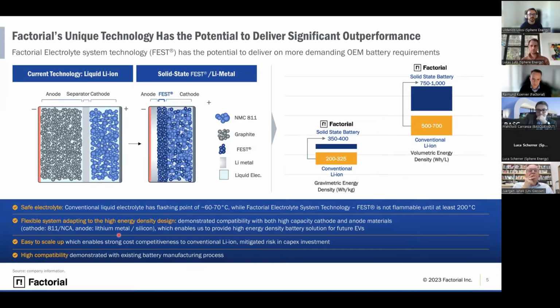Cathode side, as I mentioned before, we use commercially available materials, pretty much off the shelf. Currently, we work with NMC 811, but we've also tested beyond that. And the last 2 points, I think they're very important. It's essentially the same, but we can leverage existing lithium-ion battery equipment, and we think that we can use 80 to 85% of the existing battery production process, which is huge because it overall de-risks our technology introduction, and we can use existing equipment. We don't have to develop it ourselves, but we can make adaptations here and there. With the biggest change, of course, being the lithium metal anode. So this is the part that changes in this case.